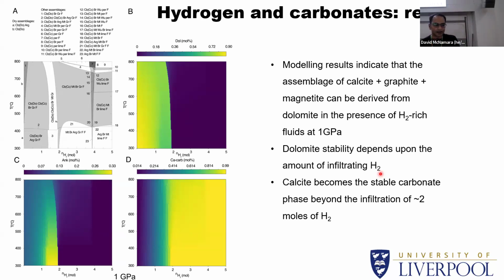And this basically models the effect of an initial assemblage consisting of just dolomite. So you have temperature along the y-axis and number of moles of hydrogen along the x-axis. And if we correlate this with our observed assemblage, we go from dolomite to a layer of dolomite and calcite, and then you go to a domain of calcite, magnetite, graphite. So we're going in a path along this way. What is interesting in this is there is a very strong correlation between the dominant carbonate composition and the amount of hydrogen that is infiltrating into the system.